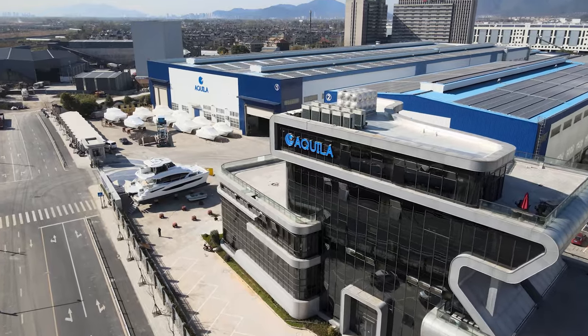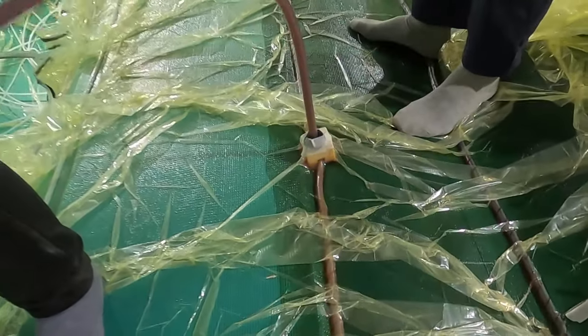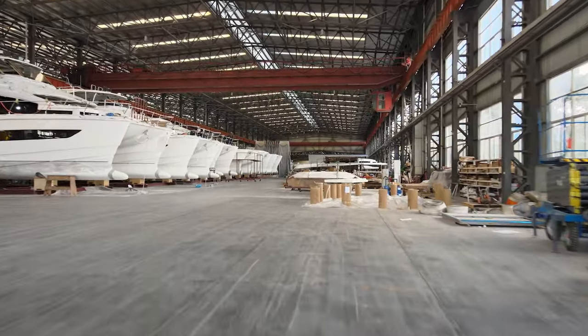The Aquila factory is one of the leading factories in the world, and from an environmental standpoint, it is one of the best — absolutely amazing. The laminating process is really closed molding, which is a resin infusion process, and we also use vinyl ester. So there's virtually zero styrene emissions into the atmosphere — really the right way to be building boats with the right materials. We do that not just with the hulls and decks, but with bulkheads, hatches, everything. Very few production builders would use resin infusion with vinyl ester throughout the entire boat.